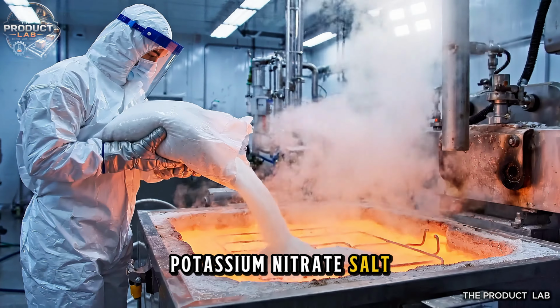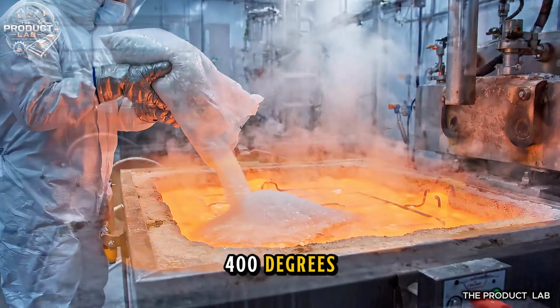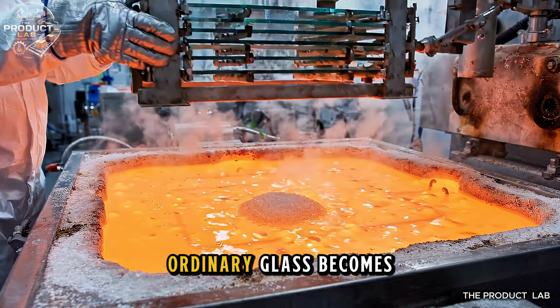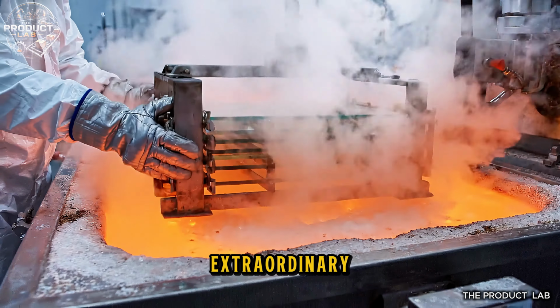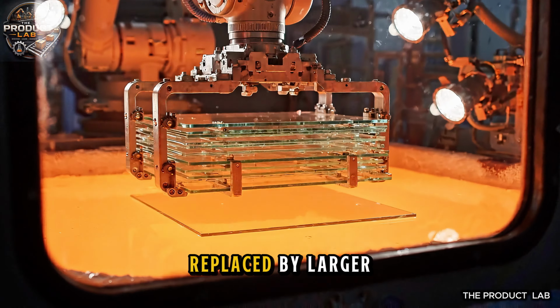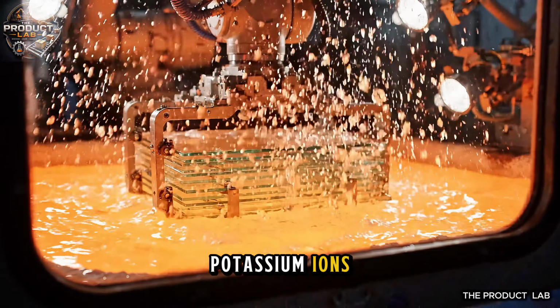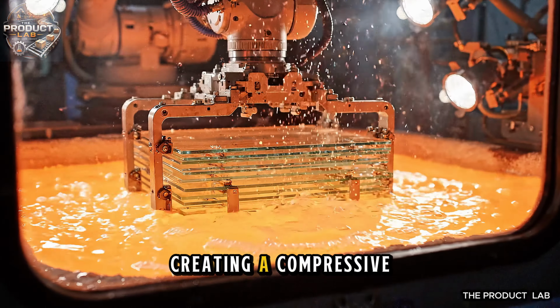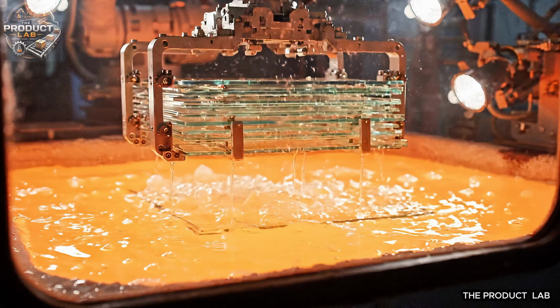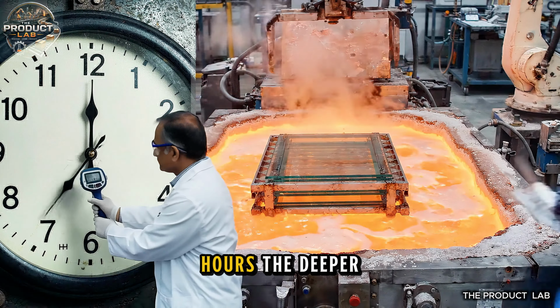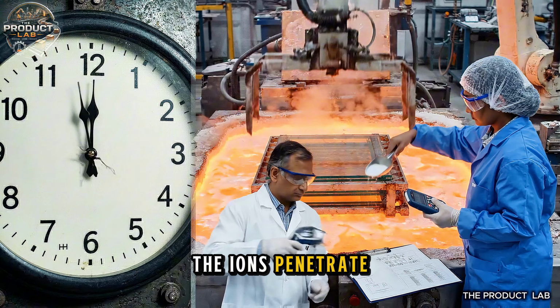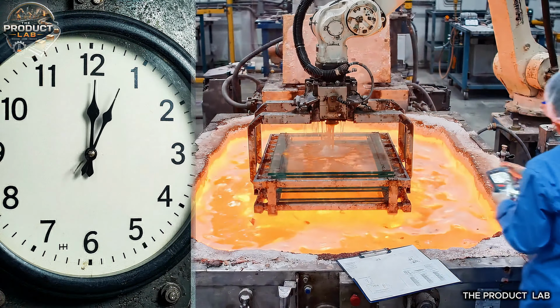Potassium nitrate salt is heated to 400 degrees. This is where ordinary glass becomes extraordinary. Sodium ions are replaced by larger potassium ions. They crowd together, creating a compressive stress layer. The exchange takes hours. The deeper the ions penetrate, the stronger the glass.